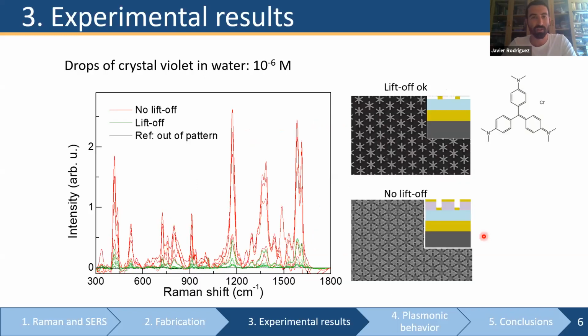But we can go a little bit further and try casting drops of a smaller concentration, in this case, 10 to the minus 6. And we are using another molecule. This is crystal violet, which you have already seen as well. And you can see that if we use the substrates with the liftoff process and without the liftoff process, we get really different results. We really discovered here that the samples without the liftoff, so with this extra gold layer on top of them, which will be a continuous gold layer with asterisk-shaped holes on that layer, give us a much better performance of these substrates, because we have seen the same peaks, but we can see them clearly. And this is something that at first surprised us, but we wanted to go a little bit deeper on that.